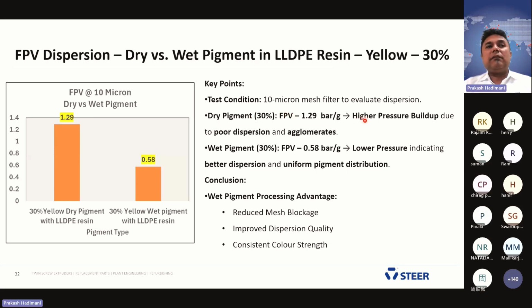Here also we observe that when you use yellow dry pigments, there is higher pressure buildup, poor dispersion and agglomerates. Again, with the wet pigments we got 0.58 bar per gram, and similarly lower pressure indicates better dispersion. And we reduce mesh blocking, improve dispersion quality and get consistent color strength in the yellow pigments also.